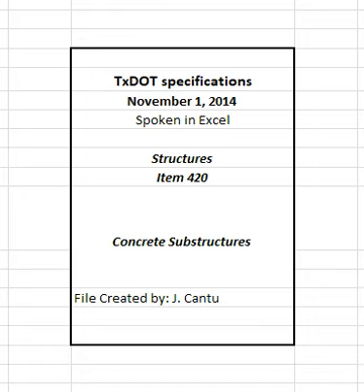4.7.1 Placing temperature. Place concrete according to the following temperature limits for the classes of concrete defined in Section 421.4.1, Classification of Concrete Mix Designs. Place Class C, F, H, K, or SS concrete only when its temperature at time of placement is between 50 degrees Fahrenheit and 95 degrees Fahrenheit.